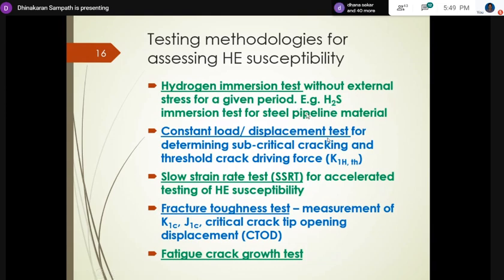If it is a seam pipe, meaning the pipe is made using welding, then they need a different strategy to expose both the body material and the weld, to see whether just in the presence of H2S, due to hydrogen blistering, it forms any blister or crack. The second one is the constant load or displacement test. This is used for measuring subcritical cracking and also the threshold crack driving force, which is the K1H threshold. This is the minimum crack tip stress field required to begin the crack propagating.